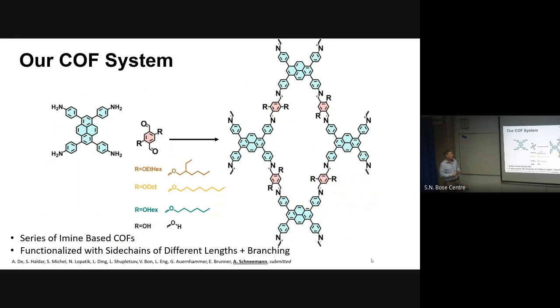So we did the same with the covalent organic framework. Here we have a pyrene-based linker. We combined it with this terephthalaldehyde, which is functionalized in the 5 position with these kinds of organic side chains. So we have a branched side chain, a hexyl chain with an ethyl group in the 2 position. We have this octyl side chain.